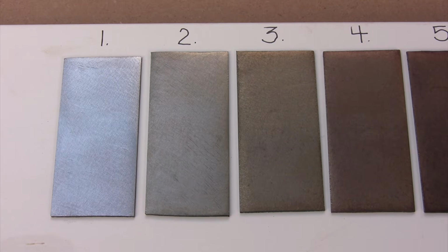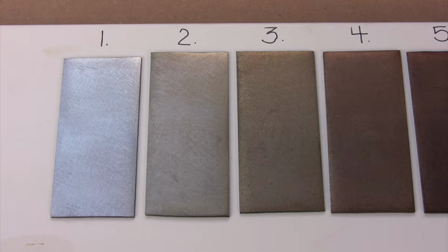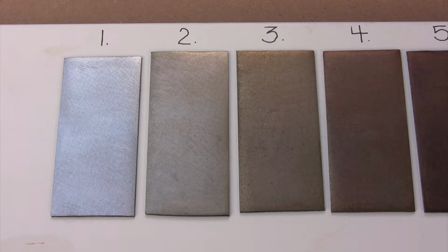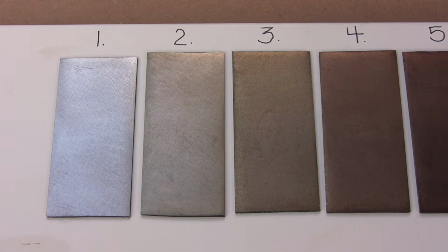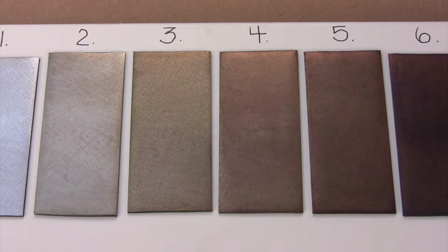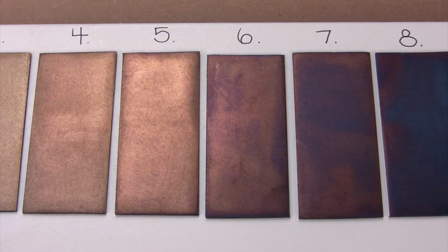Sample number 1 has had no heat applied to it. Sample number 2 is the lowest visible range that you're going to see, and it's approximately 430 degrees Fahrenheit. And it's usually identified as a light straw. Number 3 is 30 degrees hotter and is showing as a full straw color. In number 4, the straw color has turned into a light bronze. Number 5 is a dark bronze.